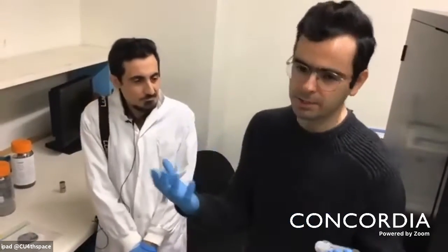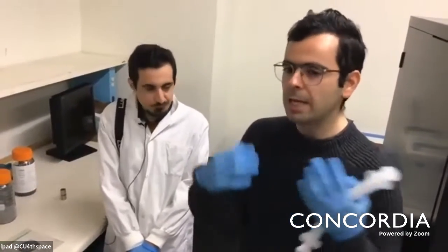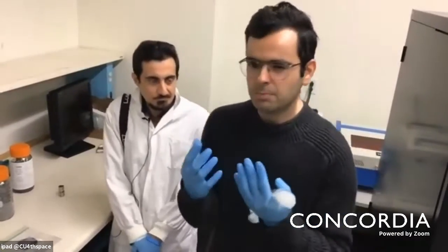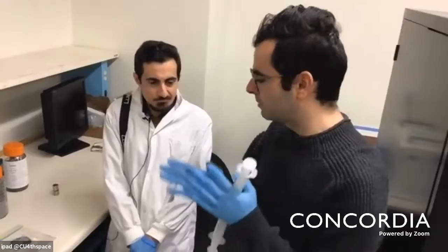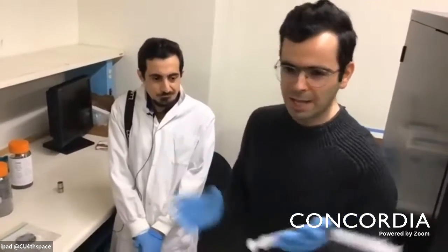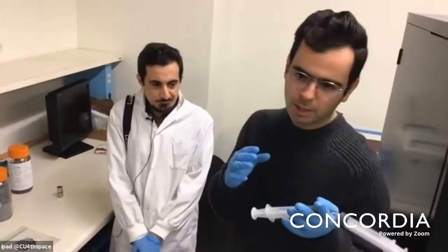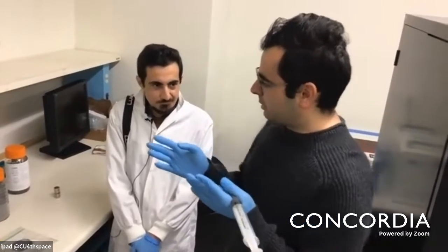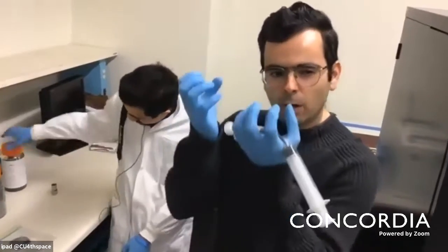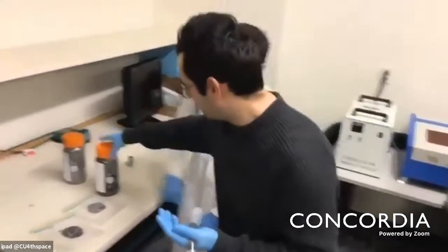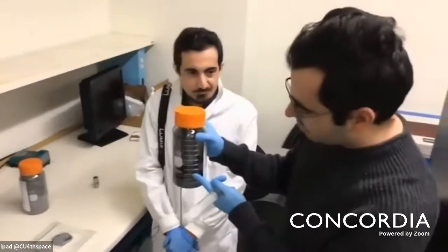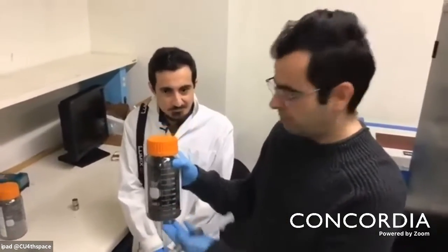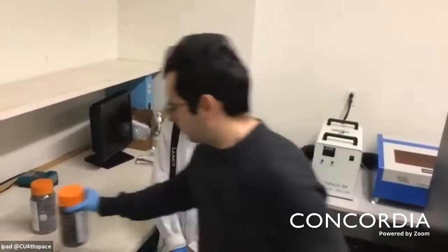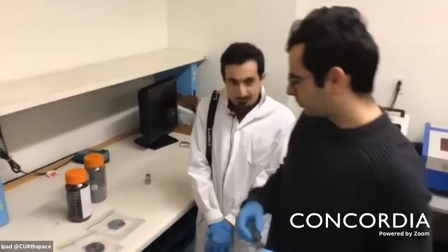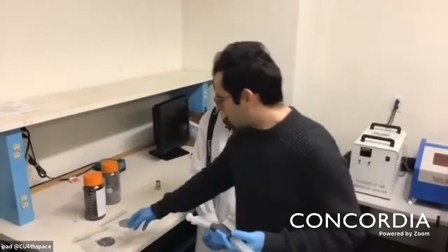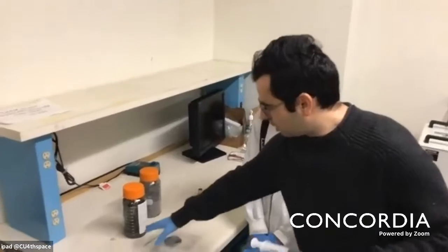This carrier can be different material. If the carrier is fluid, we would have MR fluid. If the carrier becomes solid-like material such as gel or elastomer, we will have solid-like MR material, so-called MR elastomers. There are pros and cons. MR fluids have some drawbacks, such as sedimentation of iron powder after several hours. As you can see, this iron powder sediments after several hours, so we need to disperse these MR fluids.